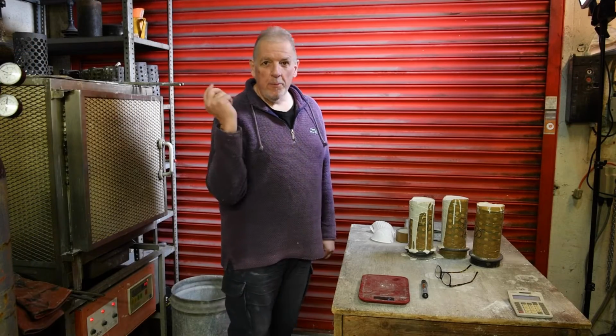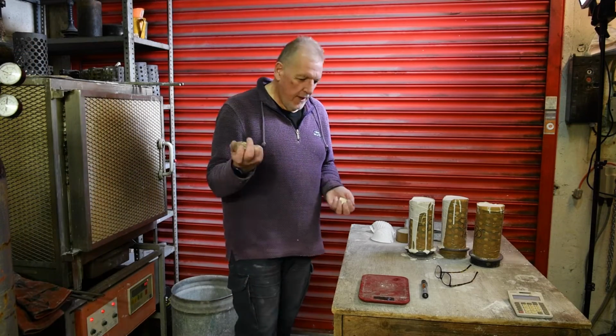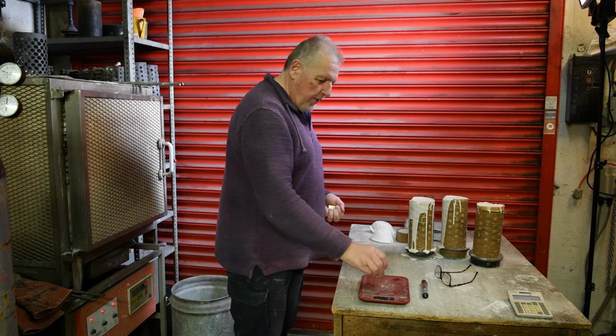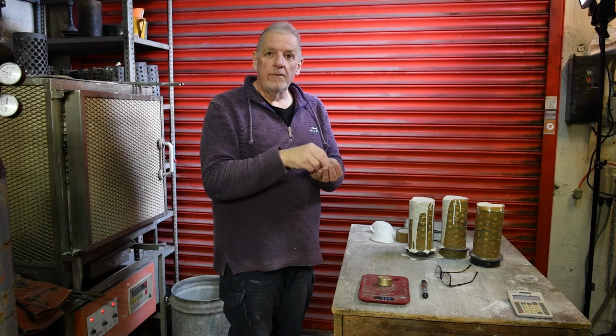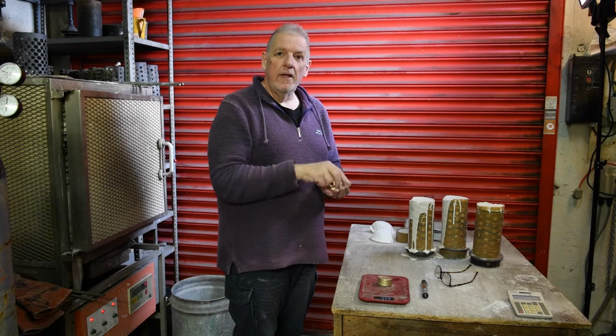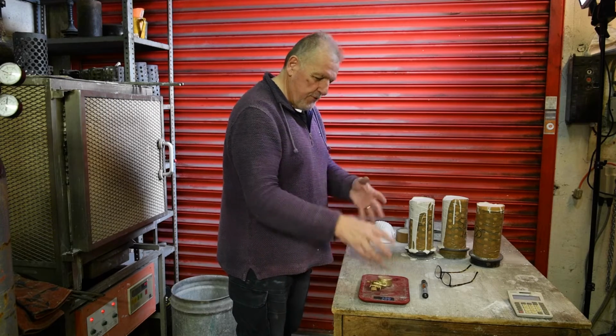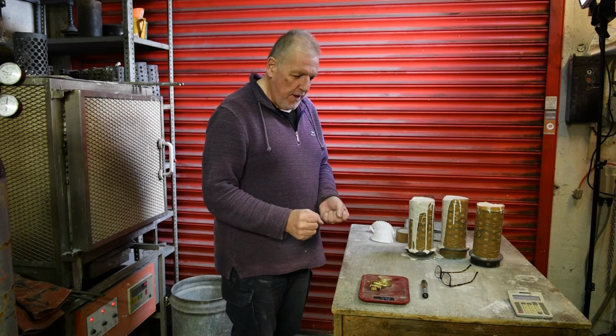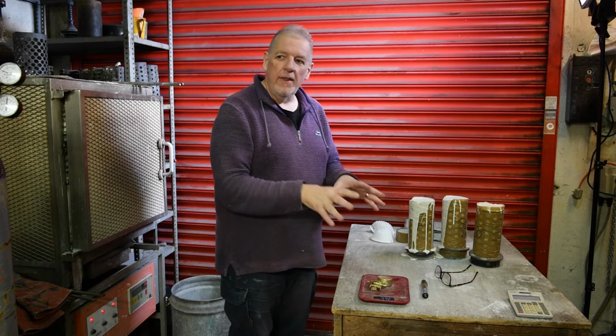Beforehand, we have to weigh out the appropriate amount of metal for each flask, which we do by putting a quantity of new metal and perhaps a quantity of old reject castings, or the sprues can be mixed in. No more than 50% old metal with 50% new metal, otherwise the castings can be ropey at best. So we have the mixture until we get the correct amount of brass, and then from that point that metal will then go into the crucible on the casting machine, and we'll be doing castings in the morning.